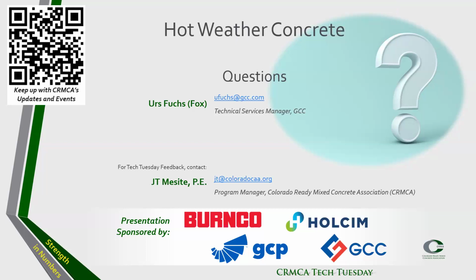Well, I was just gonna offer some advice on the high early and hot weather concrete from our experience as a producer. It's never fun to place or finish, but what we have found is in warmer weather, we need to really dose high with water reducers and leave it a very high slump. So typically in warm weather, if I'm producing a high early mix, I'm leaving the plant at like a 10-inch slump and 12% air, anticipating 5 to 6 inches of slump loss in transit and a high level of air loss. So you start very wet with a very high air, and then by the time we get there and get it on the ground, it's going off.